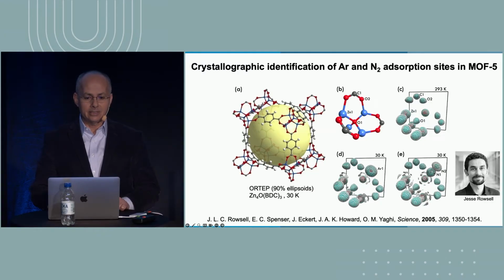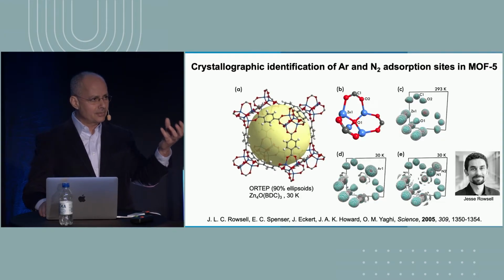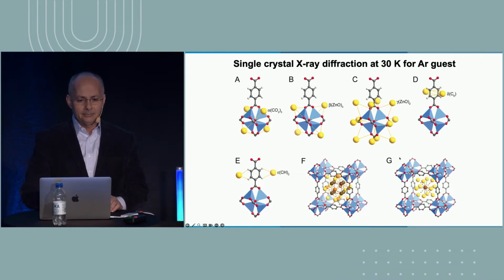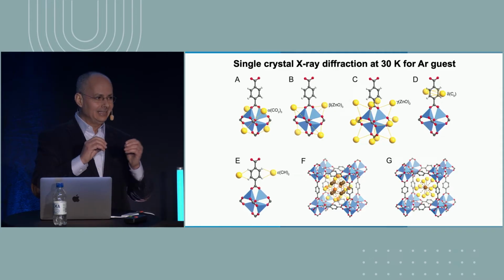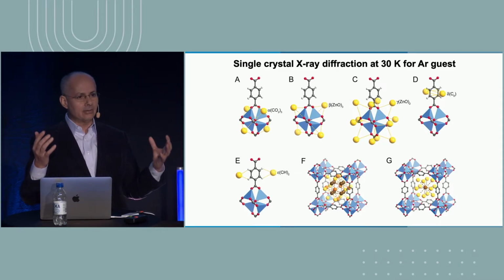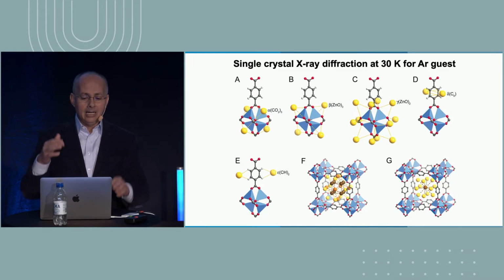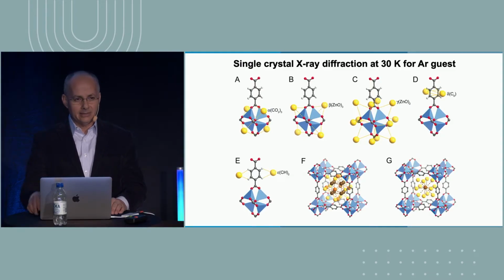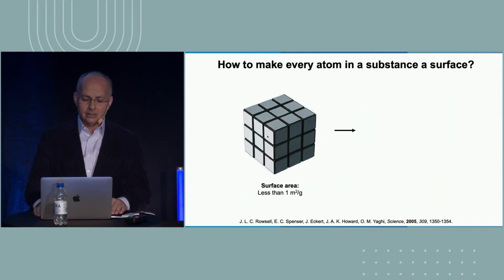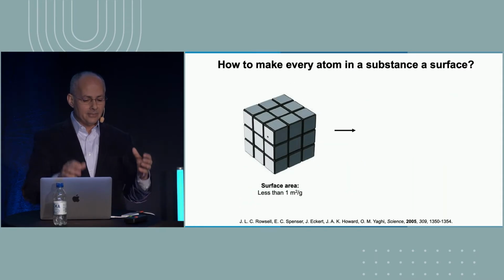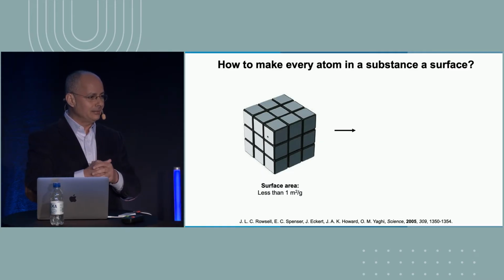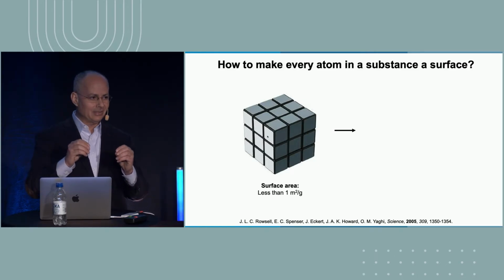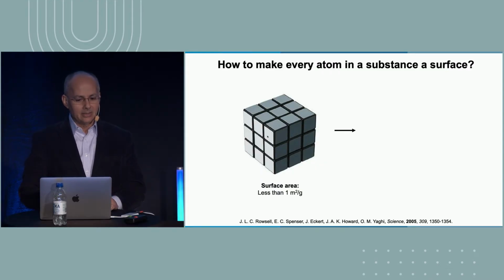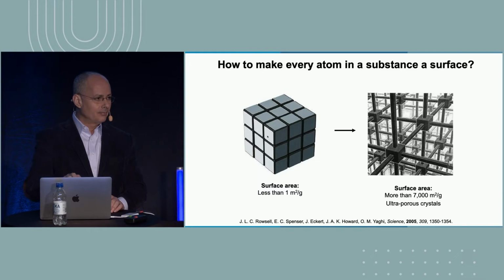This is nitrogen electron density from the X-ray single crystal diffraction. But it's not just the metal unit that's acting as an adsorptive site, but also the organic units, okay? The faces and the edges. So almost, let's say, everything you're looking at in a MOF is an adsorptive site. That's why they have this extraordinary high surface area. I like to always try to think and view things from a different angle, and again, another speaker mentioned that. You know, you take a cube that has a surface area of 1 meter square per gram, let's say a grain of sand, and I can expose every atom in that grain of sand to make a high surface area material. So really, every atom in the substance becomes a surface.